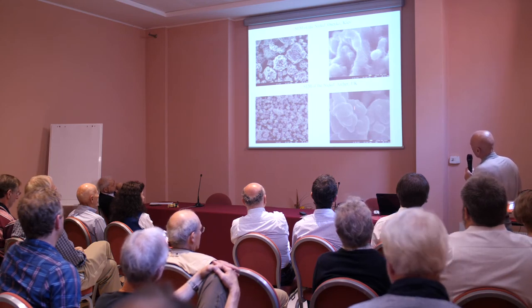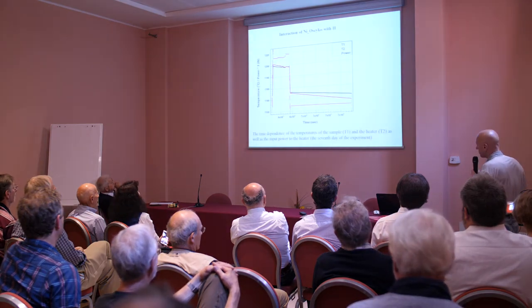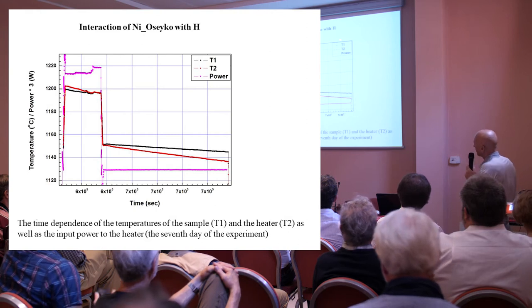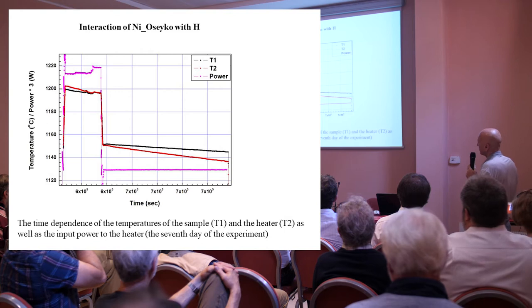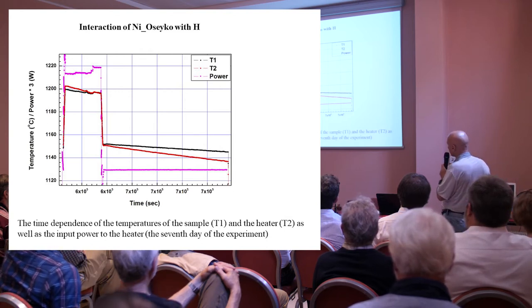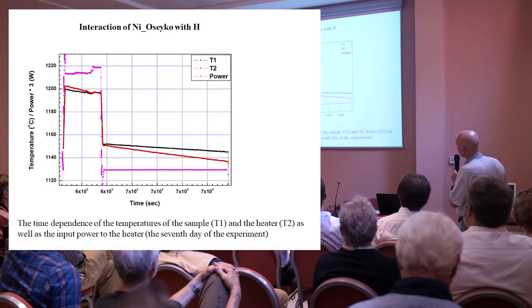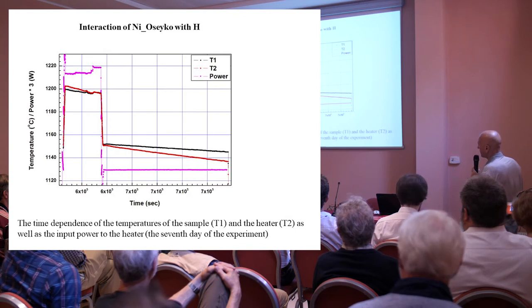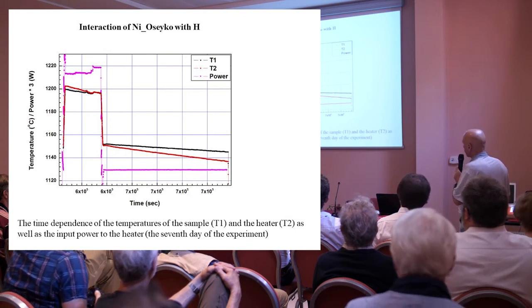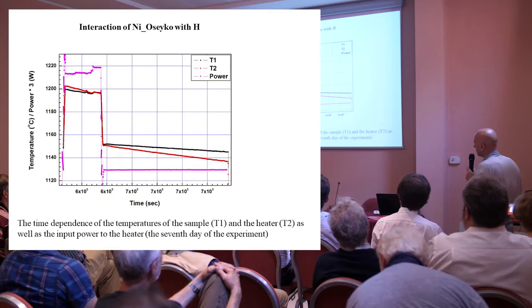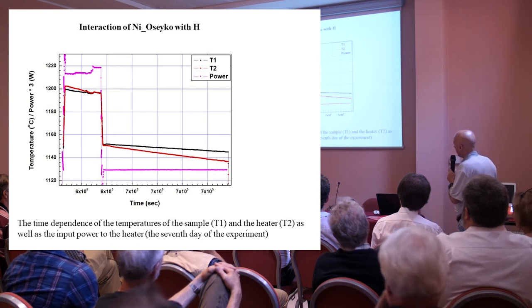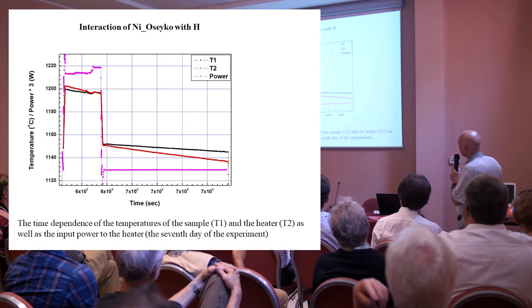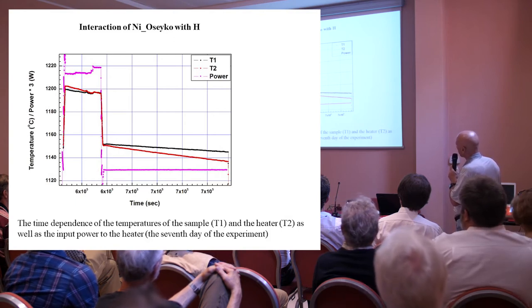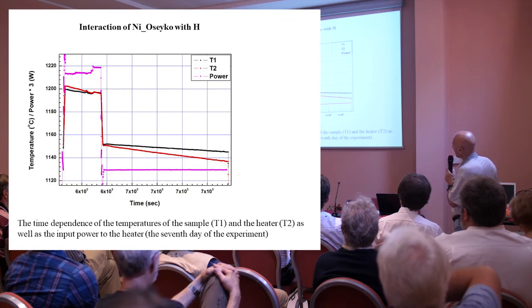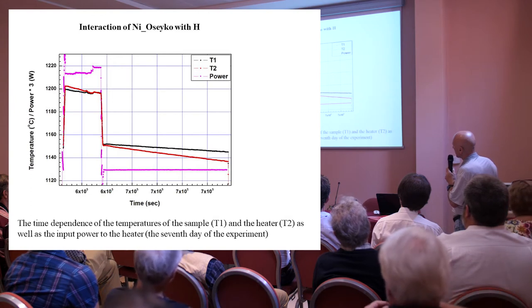It looks like a little bit more fine, but a closer look shows that their surfaces are more or less similar. And so the first experiment was just to try the basic interaction of nickel with hydrogen without lithium or aluminum, etc. Here's the time, here's the temperature. In the experiment, the nickel was preconditioned, let's say, to get rid of possible oxygen layers, etc. And then for a day or two. And then you see the red line is the temperature of the heater, and the black curve is the temperature of the fuel.